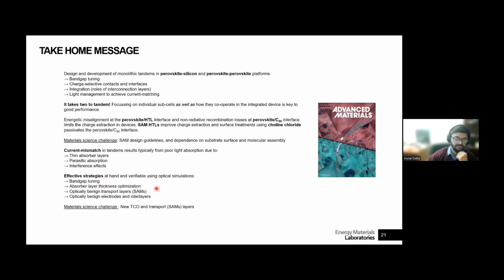And the nice thing is that you can start off in this area with optical simulation, so you don't have to go to the lab directly. The optical simulations are a very good guide for what you can do afterwards. And out of all of these, I think the most important two, where we can still change materials and tune them, are these TCO layers, which have changed quite dramatically in the last few years in the case of the perovskite-silicon tandems, but are still in the beginning for the perovskite tandems. We're still using ITO in most of the reported work, but as we show, it can go much further. And the transport layers of SAMs have come in, but I'm sure there's more to explore there.